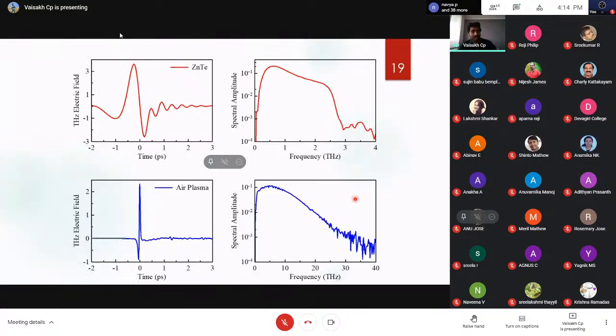But depending on the kind of emitter you use, you get different kinds of spectra. The one from zinc telluride is rather short, but you could generate terahertz pulses from air plasma, which is very broad. You can see it almost covers the entire so-called terahertz gap.